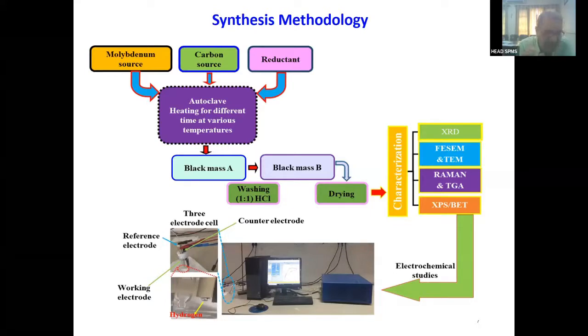So what I want to say is that because of the high temperature and the long time duration, the process becomes very, very expensive. And importantly, you are not able to convert the entire oxide into carbide, because that also depends upon the size of the oxide taken as the precursor. So what we have done is design an autoclave. Normally people use an autoclave at low temperature, something around 200 degrees. But this is a special class of autoclave which can work at very high temperature, between 600 and 800 degrees centigrade. That involves material selection and coefficient of thermal expansion, so many parameters.